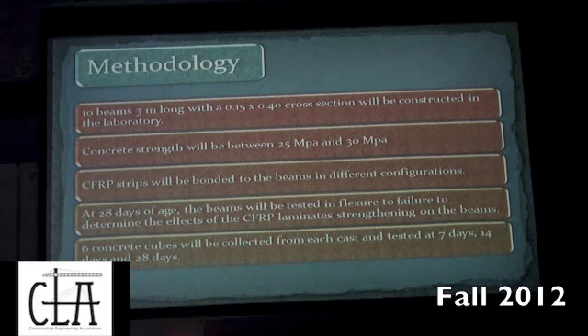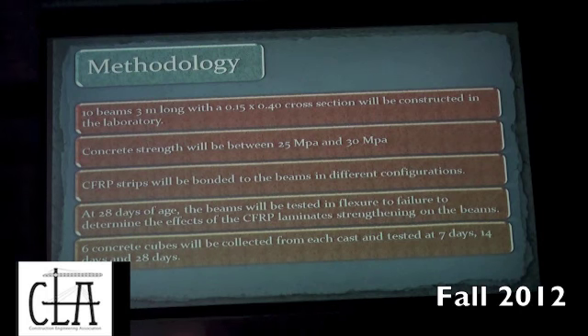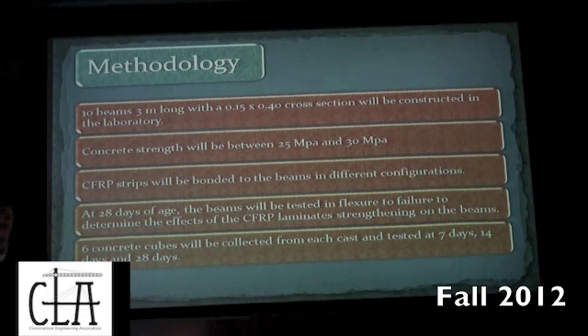Okay, so the method that we're going to be using, basically we're going to do 10 beams. They're full scale, they're 3 meters long, and have a cross section of 15 by 40 centimeters. Their strength, we designed them to be from 25 to 30 megapascal. The CFRP strips, they're going to be bonded in different configurations in each beam. And when they reach their full strength after 28 days, we'll be testing them for fracture and failure. And this will determine the effect of the CFRP laminates, how it affects the strength.